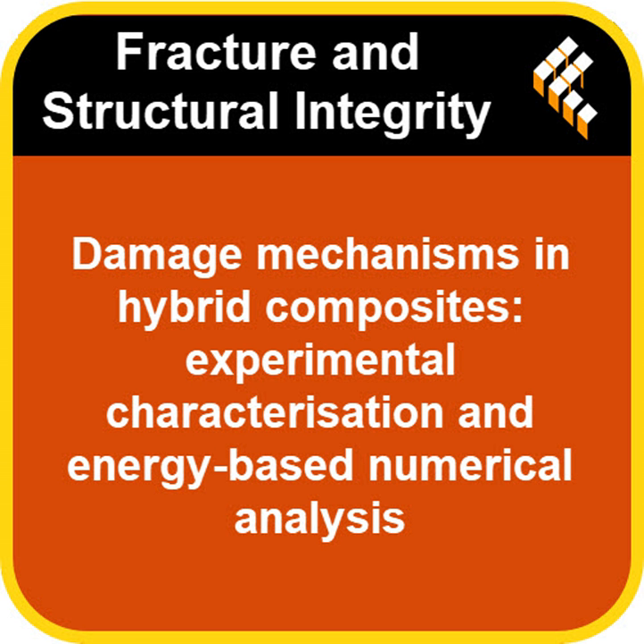They set specific values for things like how stiff that interface is, how much stress it can handle before damage starts, and crucially, how much energy is needed for the layers to completely separate. They even included interaction parameters. Wow, it sounds like they really got down to the nitty-gritty of how these materials fall apart.